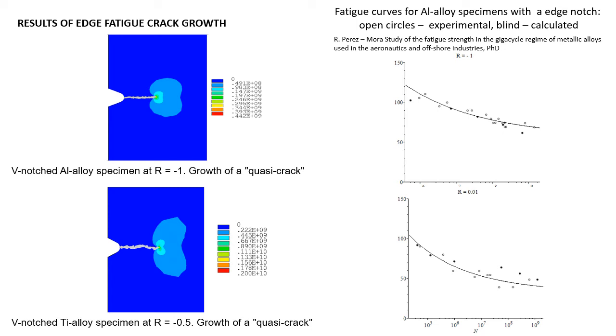The notch specimen was subjected to ultrasonic loading in order to get the crack-like structure and the developing zone of fatigue damage accumulation here. At the beginning, the local stress was below the classical fatigue limit, and the driving mechanism was associated with the very high cycle fatigue region. After a certain length of the crack-like structure, the mechanism turned to propagation in the high cycle fatigue region.